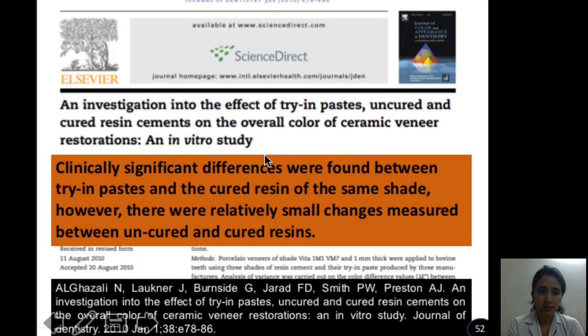Now, there was a study, an investigation into the effect of trying paste, uncured and cured resin cement on the overall color of ceramic veneer restoration, an in vitro study, in which they concluded that clinically significant differences were found between the trying paste and the cured resin of the same shade. However, there were relatively small changes measured between uncured and cured resin.